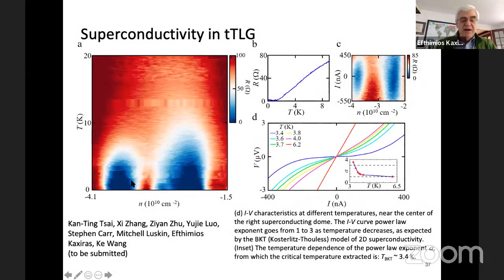So this is a plot similar to the ones that I showed you earlier for bilayer graphene. Again, here you see the resistance as a function of current, and you see this flat region, which is zero resistance, superconductivity, and these are the domes, the superconducting domes, the regions where the superconductivity appears. Moreover, the critical temperature at which this occurs is 3.5 degrees, almost a factor of three higher temperature to observe superconductivity, which is always desirable. So this is very interesting and very promising.